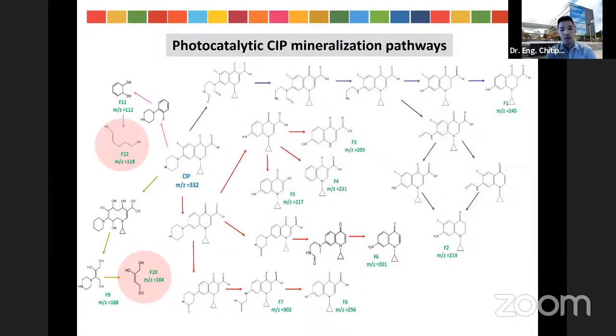And also we checked the degradation byproducts using LC mass analysis, or LCMS. And from the LC mass result, we can find some small fragments of the CIP, which are marked in the red circle, F12 and F10. So the presence of the aliphatic chain carbon, which is a fragment of the CIP, confirms the destruction of the CIP molecule during the photocatalysis.